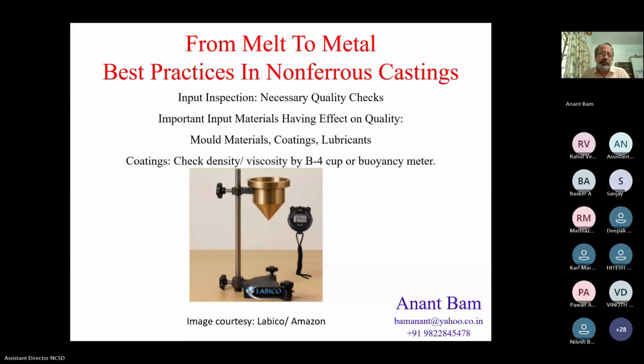For example, the white coating, which we call die coat 140. If it has a viscosity of B4 cup 20 or 22 seconds, then in a single application, it can deliver a dry film thickness of 100 plus microns, 100 to 150 microns. The same coating, if the B4 cup empties in 16 seconds, will deliver a dry film thickness of maybe 50 to 70 microns.